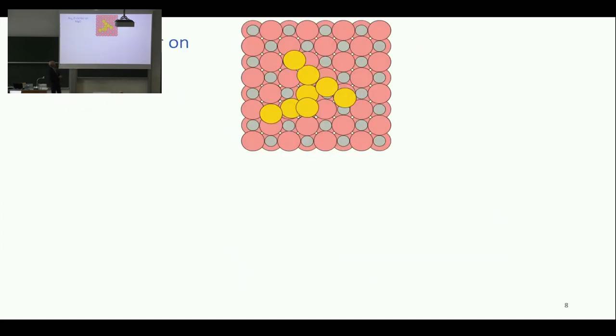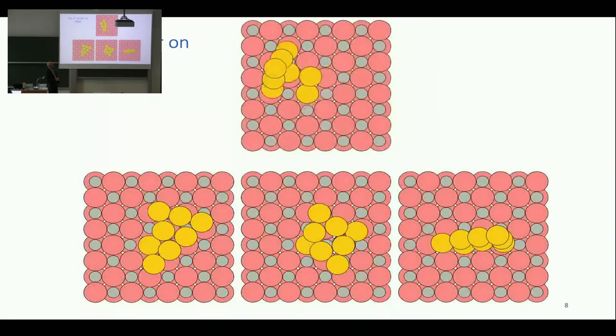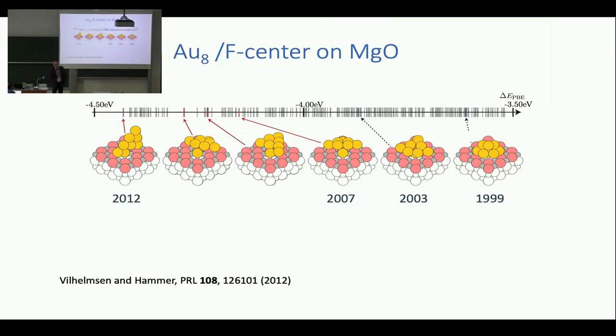Let me give an example. We take the gold 8 system and search for the optimum structure. Something comes out — that's actually one of those we reported previously — but then there are others. When we place them on an energy scale, they are way better than the ones found via human imagination. Some of them are just rotated 45 degrees compared to each other. It takes a human to have that idea, or it takes a machine and very many attempts to get that idea.